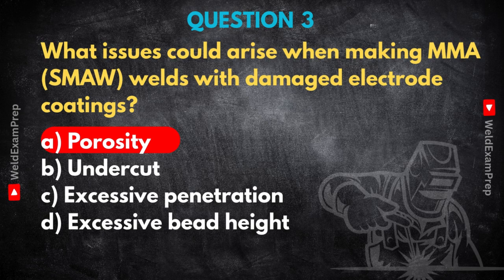Precisely. They form little gas bubbles, voids within the solidified weld. That's porosity. So while other things might go wrong with bad technique, the damaged coating directly leads to that atmospheric contamination. That's the most direct link, yes. You lose the shield, you invite porosity, it compromises the weld from the inside out.